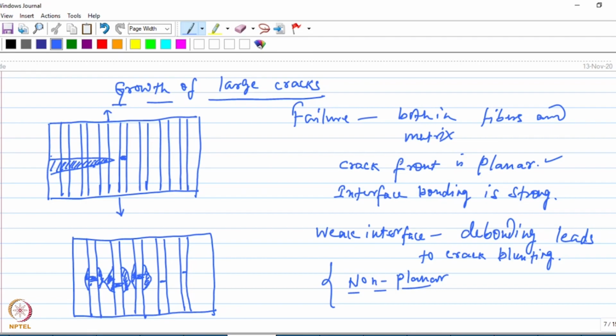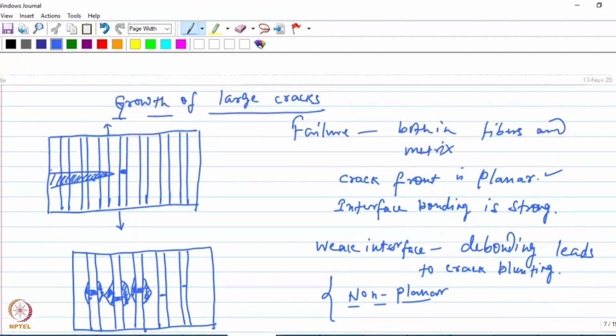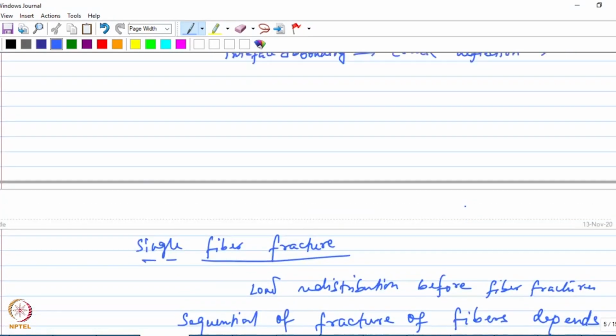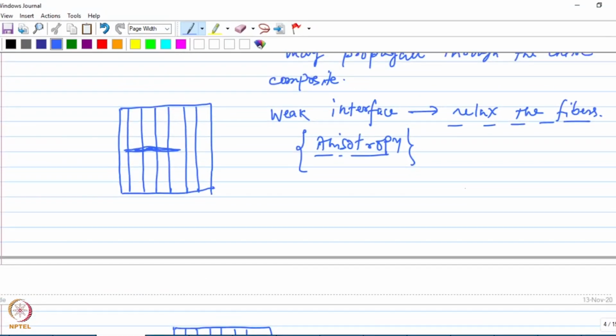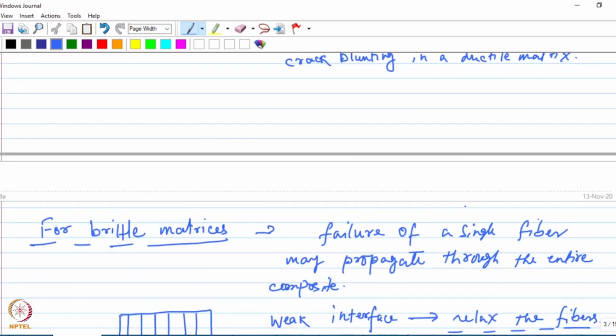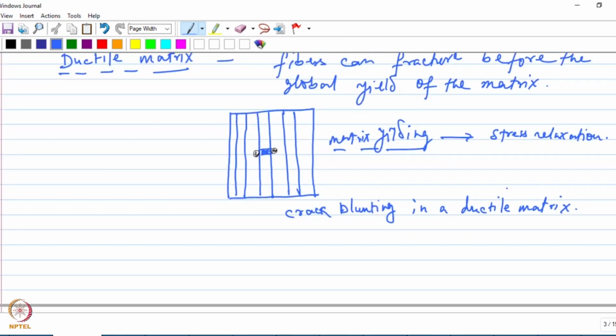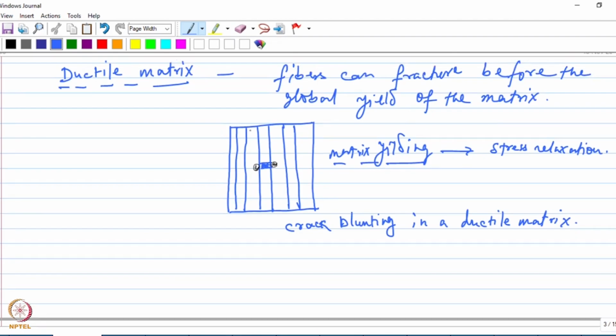So to quickly summarize this fracture behavior of fiber reinforced composites, we can say that when you talk about the entire fracture of the composite material, you need to take into account the matrix behavior and the fiber matrix interface. Okay, so depending on that, the crack will behave or propagate differently. And matrix properties such as the ductility of the matrix will have a role to play on the propagation of the crack. When it is a ductile matrix, the yielding of the matrix material at the broken fiber ends leads to stress relaxation, and that will prevent the propagation of the crack.